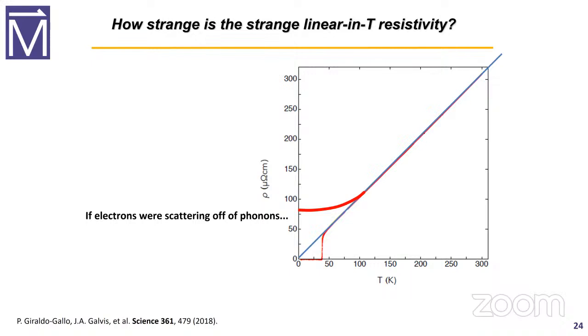Then as you increase temperature from zero, your phonons form a black body distribution curve of population because they're bosons. And so you're generating many, many new phonons that the electrons would scatter off of. So this is the curve you expect. And then if you go to very high temperatures, eventually your electron is going to scatter off of every atom that it encounters. Its mean free path will get so short that it equals the interatomic spacing. And then the resistance will level off because it can't scatter any more than that. And this just keeps going up. How can your electrons be scattering off of more than every atom?